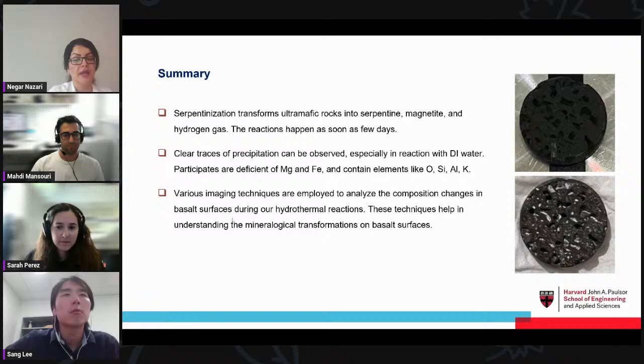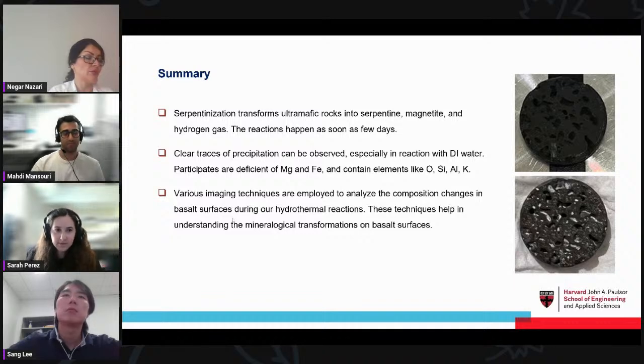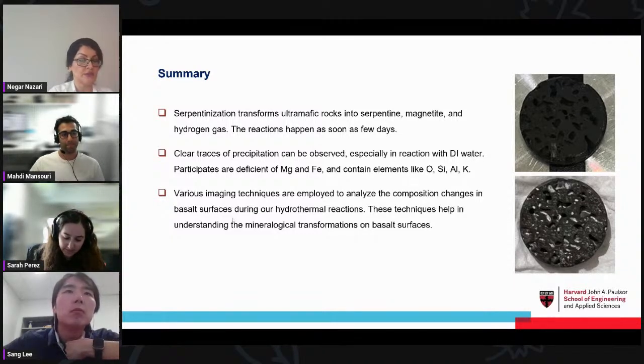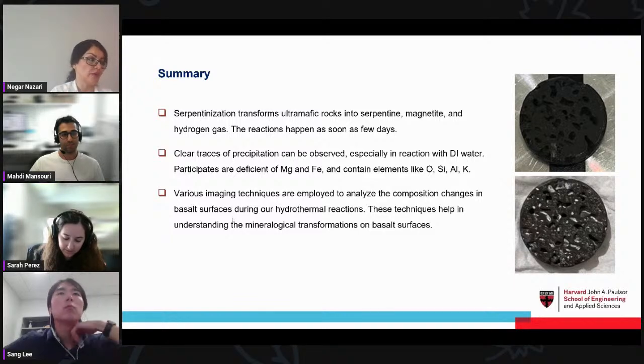of the rock. And we used various imaging techniques, from confocal microscopy to SEM with EDS, and also we conducted NMR analysis. I did not include it here because of the time limitation. We analyzed the composition changes in basalt surfaces during the hydrothermal reaction. These techniques helped us to understand the mineralogical transformation on basalt surfaces. The next step would be to understand what we are producing. In terms of the dissolution, a colleague of mine checked the composition of the water that we produce in the effluent, and we observed that the concentration of calcium, sodium, and potassium in the effluent increased by a few folds, in a very short period of time, as small as a few days.